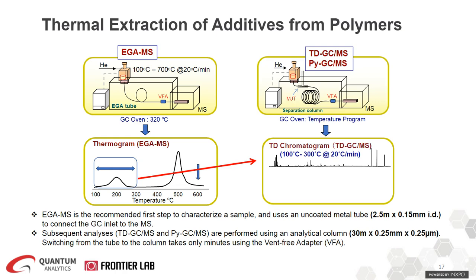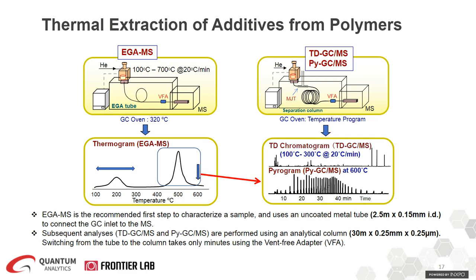tube to a separation column. That is done very quickly and easily from the vent-free GCMS adapter. And then you program your furnace from 100 to 300, and you'll obtain a TD chromatogram. So now you are thermally extracting all those additives and volatiles from the mixture. And now to analyze the second peak from your EGA, this time you'll do the second analysis, and we call this a flash pyrolysis because you heat up your furnace high temperature around 600 C.